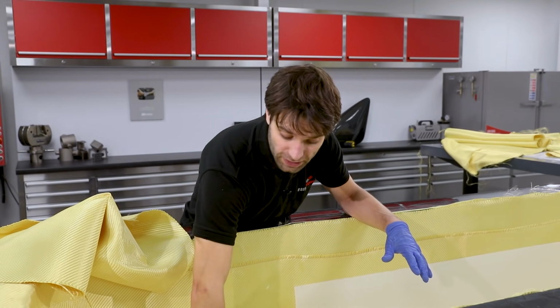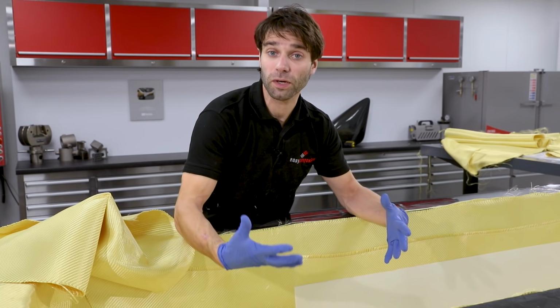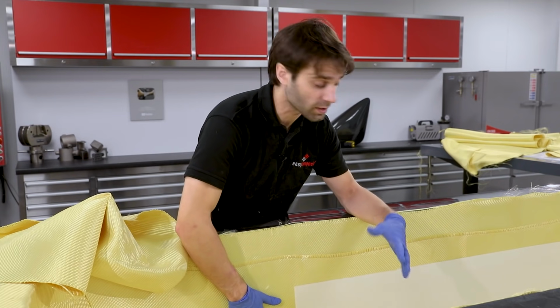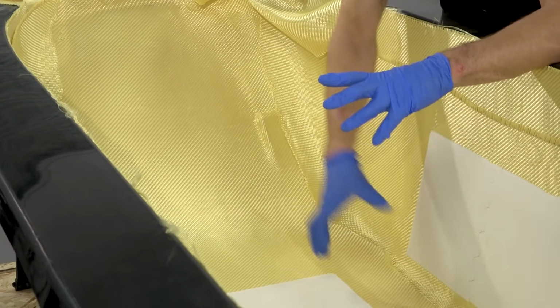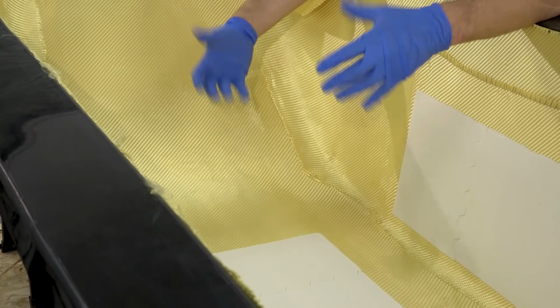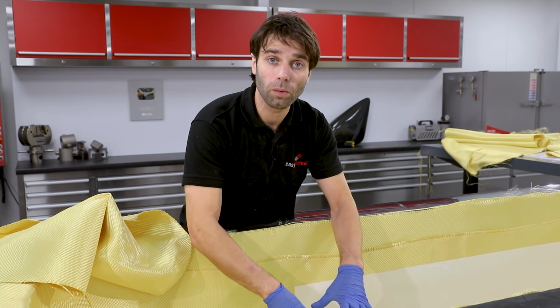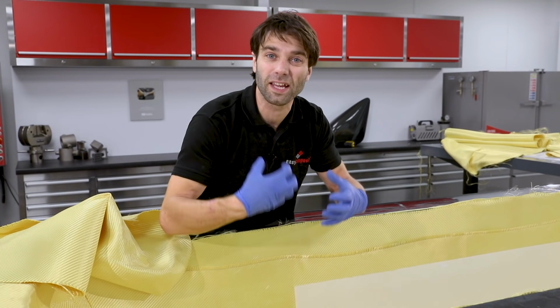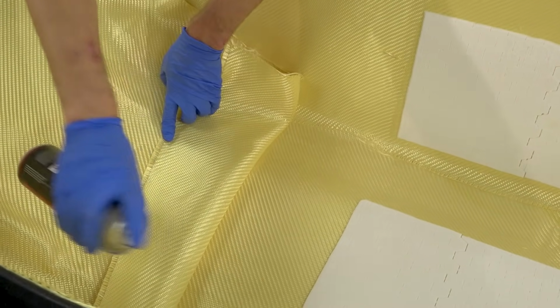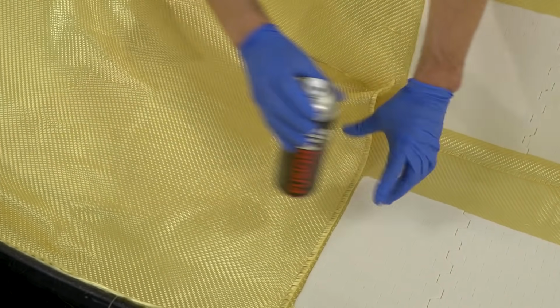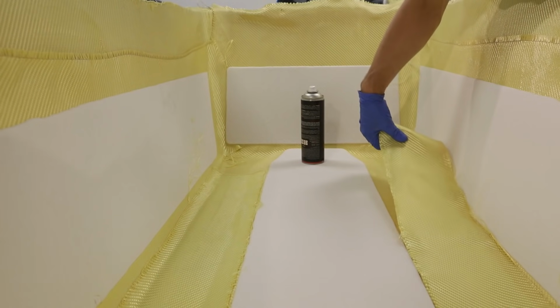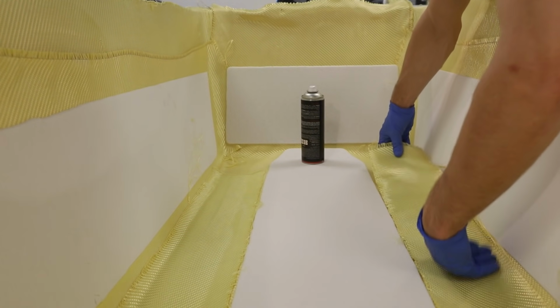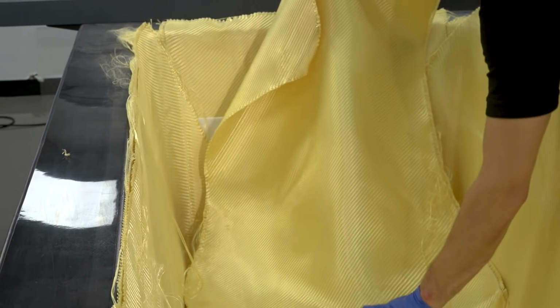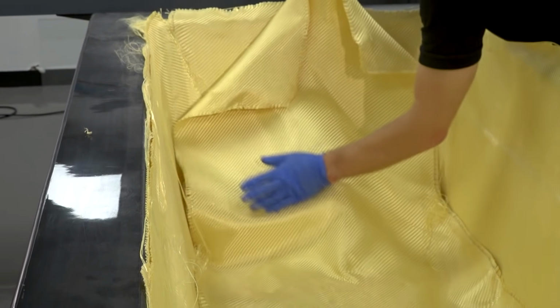Around the front and the nose here, these are going to be encountering frequent impacts, likewise on the shoulders. And also the runners themselves are bearing nearly all of the load of the sledge. So in these areas, instead of having core material, we're going to go with a solid laminate to make it particularly tough. The additional reinforcements are butted up to the core material, and then the inner two plies are laid over this. The entire layup of this sledge is a very quick and clean process and was completed in less than an hour.